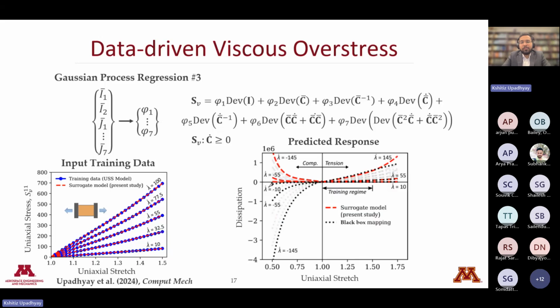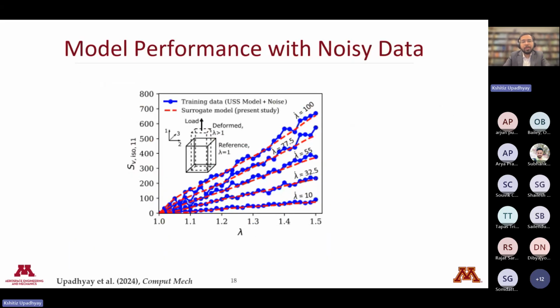On closer investigation, we found out that that was because of the negative dissipation predicted by the black box mapping, which is not possible. Now, because our model understands physics, it understands that the dissipation has to be positive. It doesn't make such mistakes, and it makes reasonable predictions far outside the training regime. We also tried to observe the predictions for noisy data to mimic what real experimental data would look like. And as expected, the GPR models do exceptionally well with noisy data.